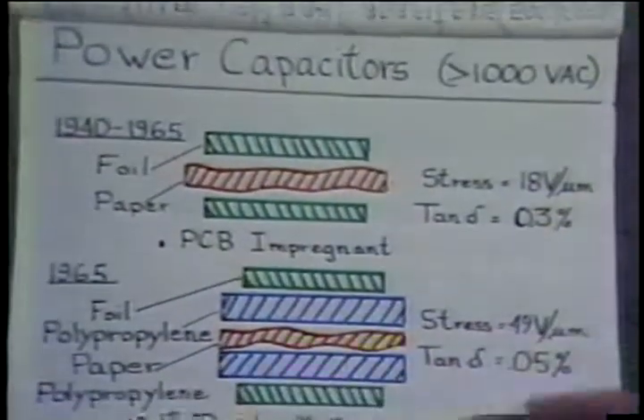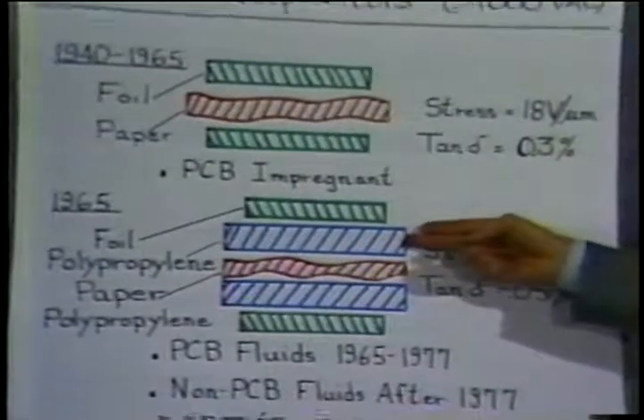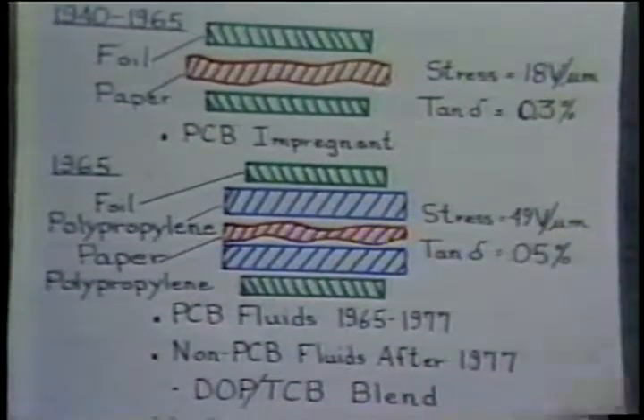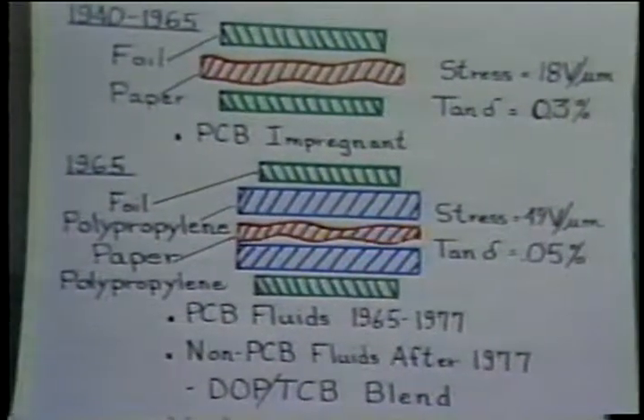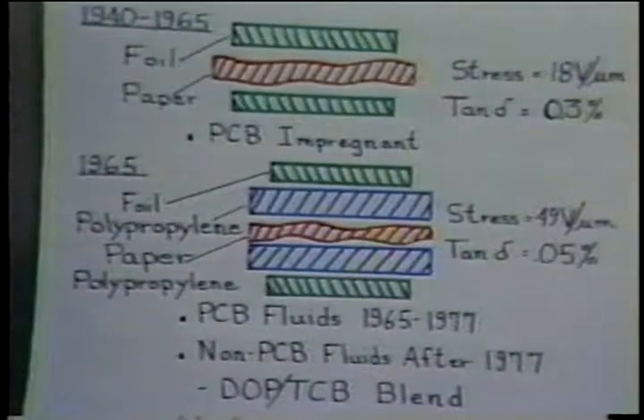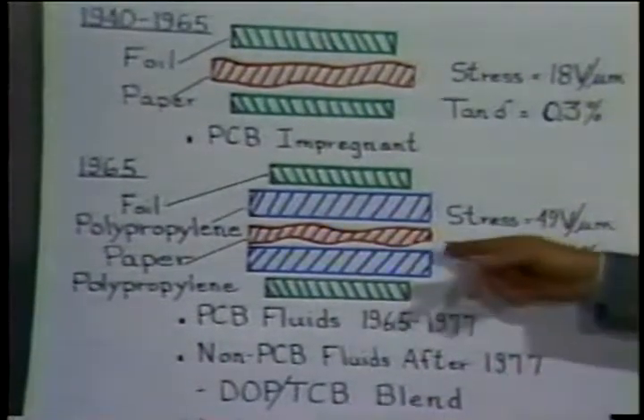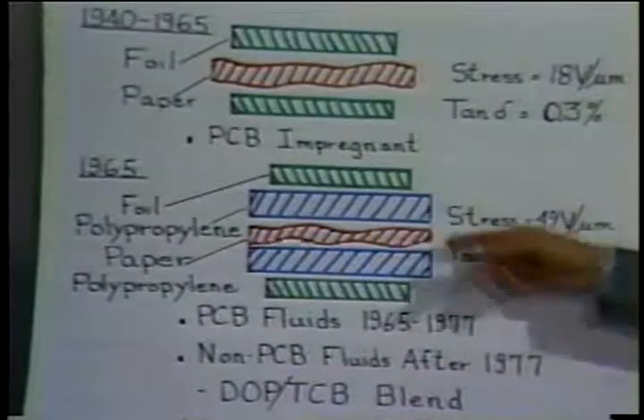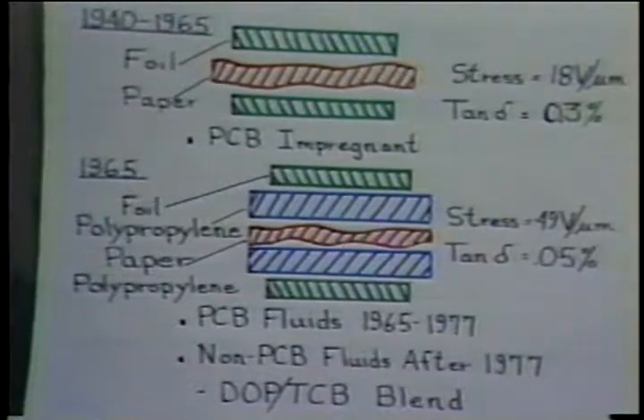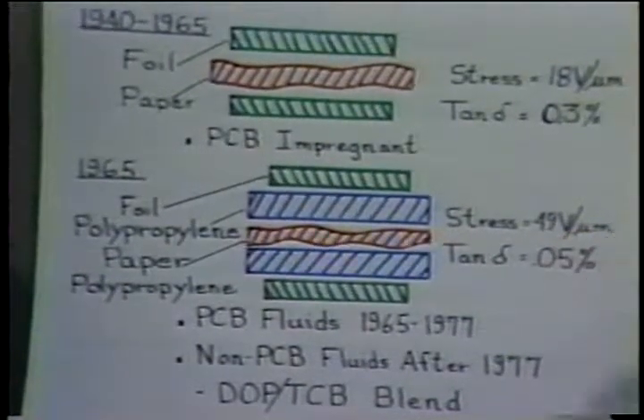In 1965, a major change occurred in the capacitor industry. That was the introduction of polypropylene film as a dielectric material. It had a dramatic effect on the dissipation factor, reducing the capacitor dissipation factor to 0.05%. The stresses also increased to 49 volts per micron. Had a very dramatic effect on the size of that capacitor.